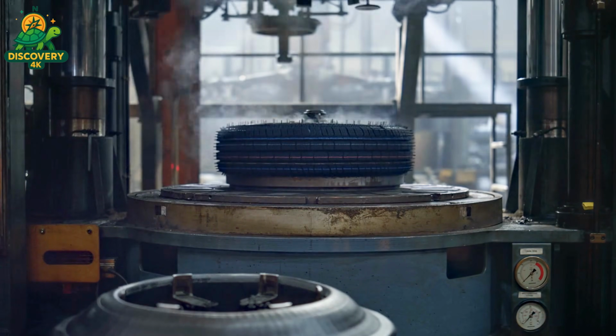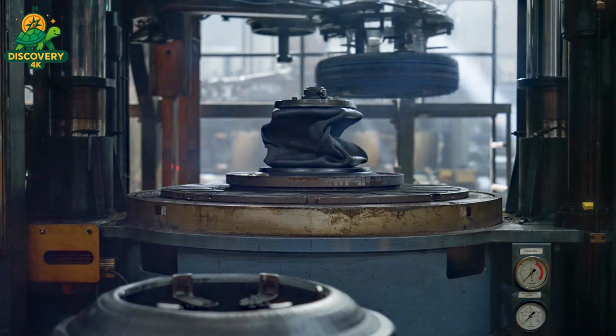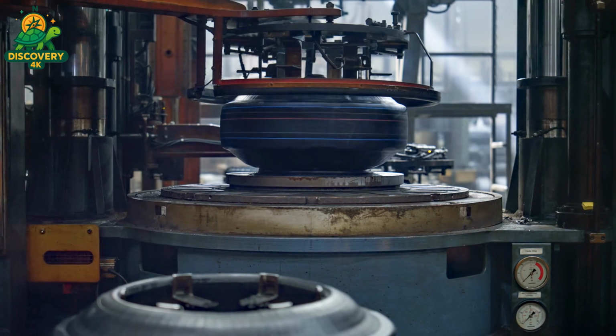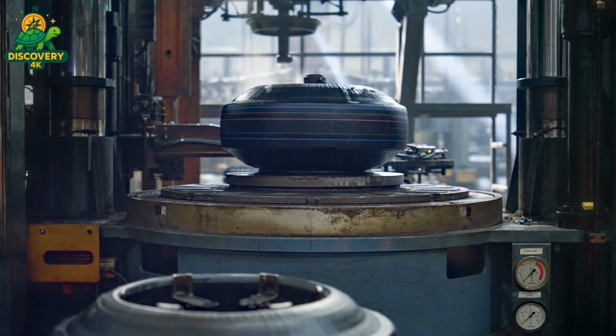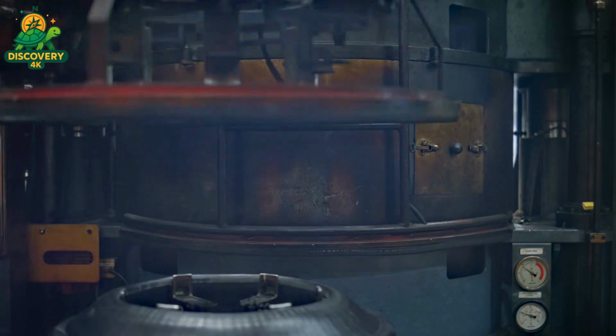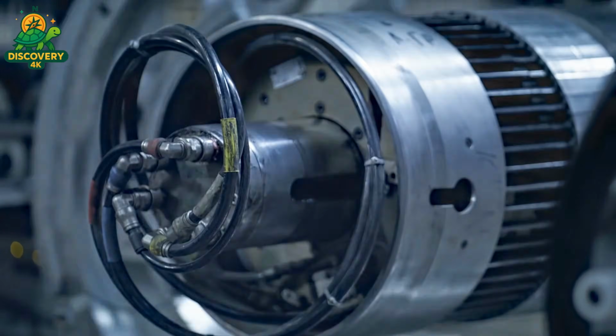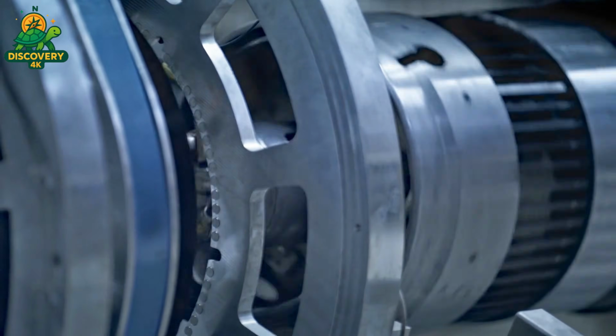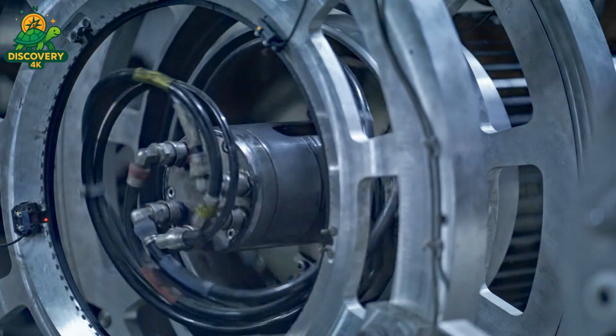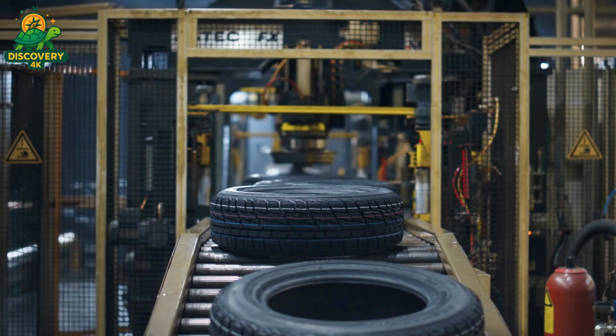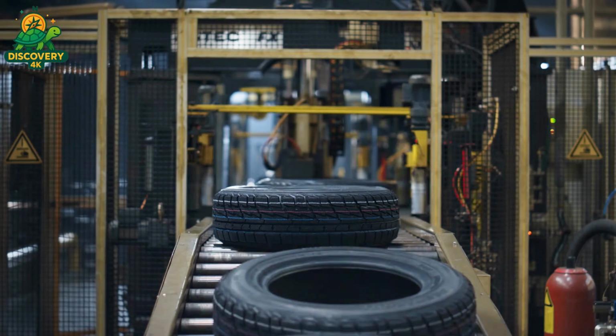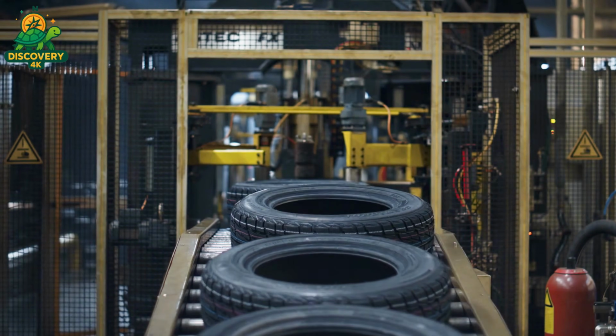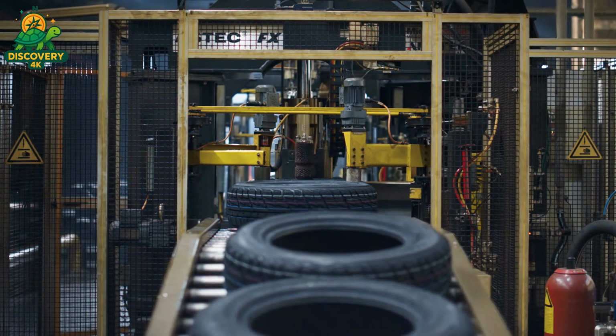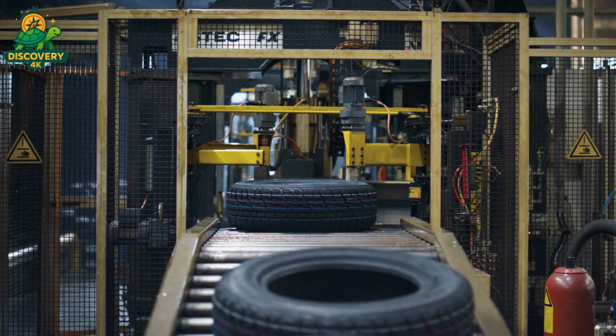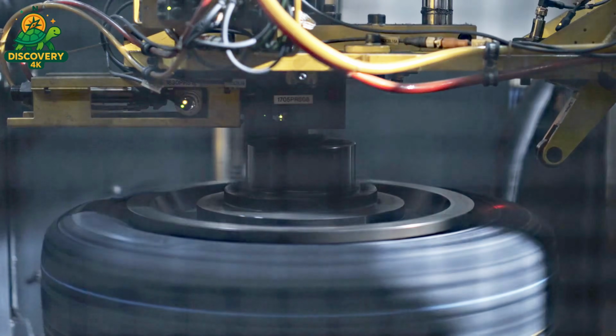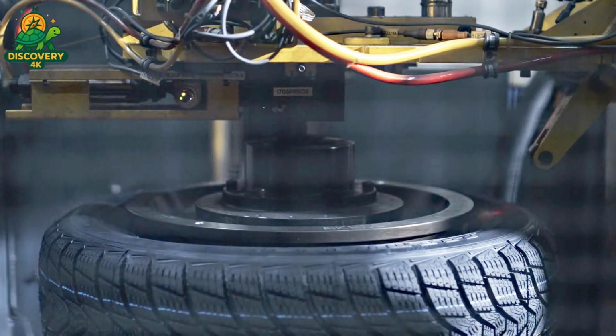In this process, the green tire is placed inside a large mold, shaped like the final product. The mold is lined with engraved patterns, which will form the tread and sidewall details. Then, a rubber bladder is inserted into the center of the tire and filled with hot steam or gas. As pressure builds, up to several hundred psi, it forces the tire outward against the mold walls. At the same time, the entire mold is heated to around 170 degrees Celsius, 340 degrees Fahrenheit. This activates a chemical process where sulfur cross-links the rubber molecules, making the material harder, more elastic, and permanently bonded.